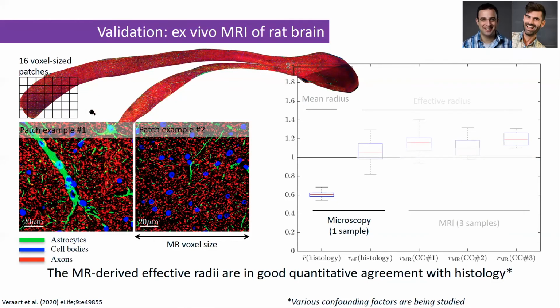A more quantitative analysis followed. We focused on the genu of the corpus callosum, and we identified 16 patches. And one patch had the same size as an imaging voxel, which was about 100 micrometer by 100 micrometer. Within each patch, we did staining of axons, cell bodies, astrocytes, but we focused on the axons. And we quantified the radii of those axons. So within every patch, we can make a distribution. And from a distribution, you can measure the average, and that's what we would typically report in a histological analysis. We can do this for 16 patches, so we can make a box plot of that. And you see this precise box plot over here.